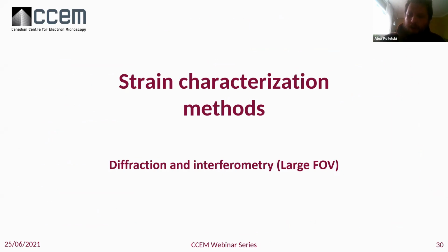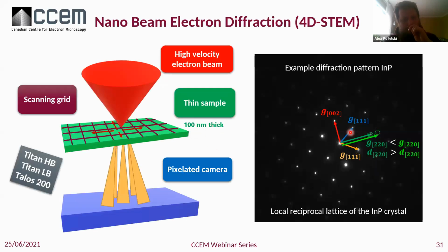Now we're going to go towards diffraction interferometry. The idea here is to break this field of view limitation. There are some nice high resolution images now that can go to, for example, 1 micron or 2 microns. Here you have two different approaches to break this with different strategies. We're going to start with diffraction, and the idea is, instead of measuring the deformation from the crystal structure directly, to take a signal that represents the crystal structure but that can be averaged over a large area. So, for example, instead of taking the direct image of the crystalline periodicity, you're going to take the diffraction of it.